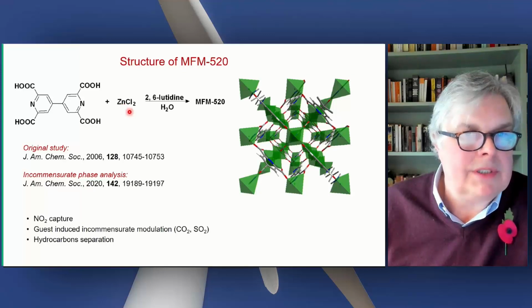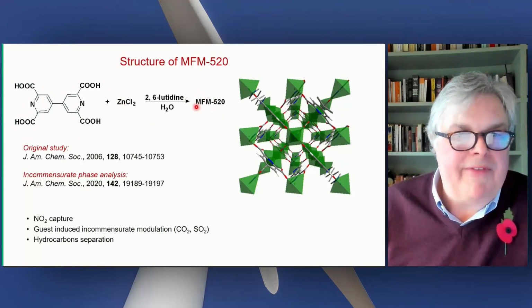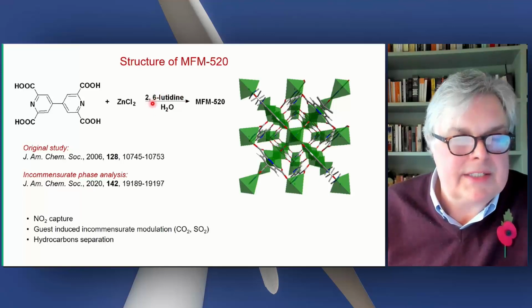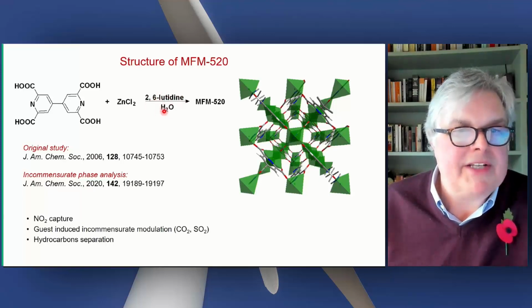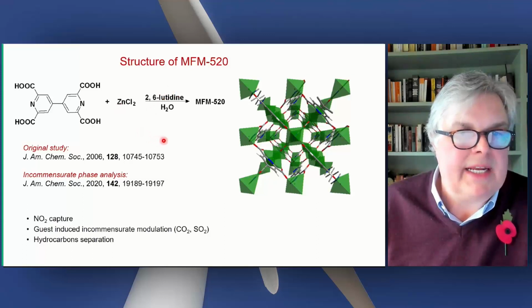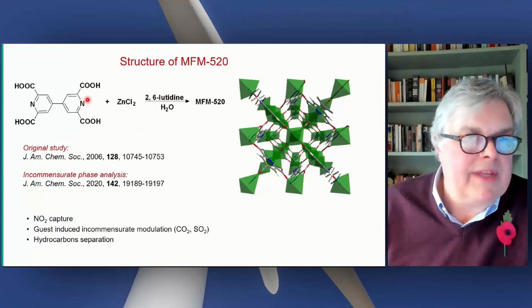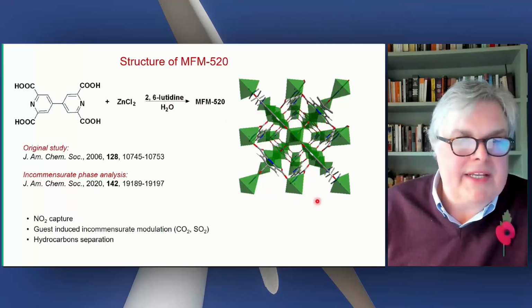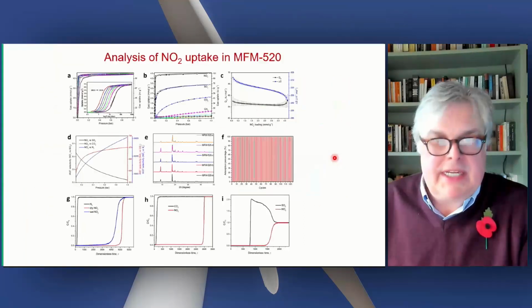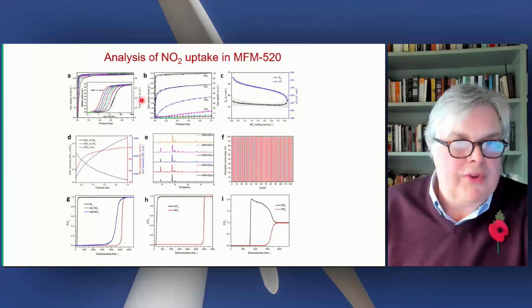It is a zinc compound. It gives you MFM-520. 2,6-lutidine is a base, 2,6-dimethylpyridine. It's a very strong base, but it doesn't coordinate to zinc. So therefore, this does not get protonated under these conditions. You can form this MFM-520 material. I won't go through this analysis.